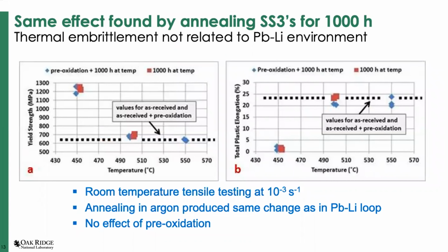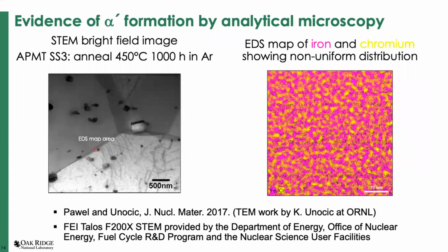But the one thing we were able to prove in this study was that if we annealed the specimens at the same temperature, we get the same effect, in the same temperature range, I should say. We only selected 3 temperatures to evaluate and got the same type of embrittlement going on. So again, it wasn't the lead lithium environment per se that we were doing the environmental test. The alloys performed very well at that temperature, but again, can use our SS3 specimen and do some nice TEM work.